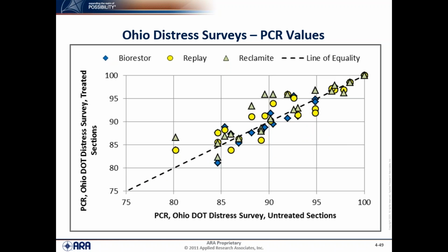This is now the PCR data. We took the distresses using the Ohio distress surveys. We also took the distresses from the long-term pavement performance survey, and we calculated the PCR values in accordance with ODOT's procedure. The x-axis shows the PCR of the Ohio distress surveys for the untreated sections, and the y-axis is the PCR value for the treated sections. You can see that as we go over time to lower PCR values for the control sections, some of the treated sections have, on average, a little bit higher PCR value, indicating a little bit less distress.